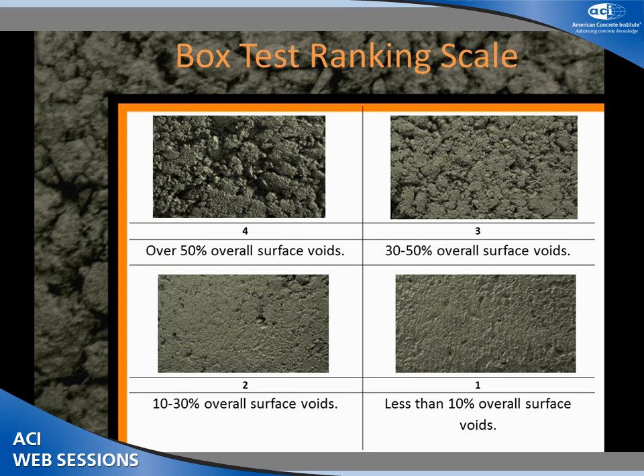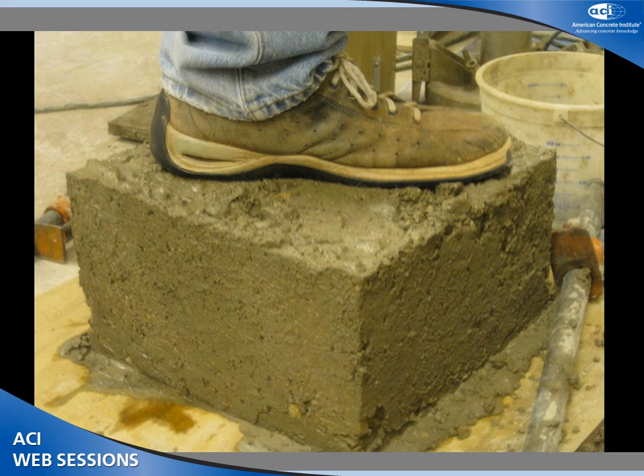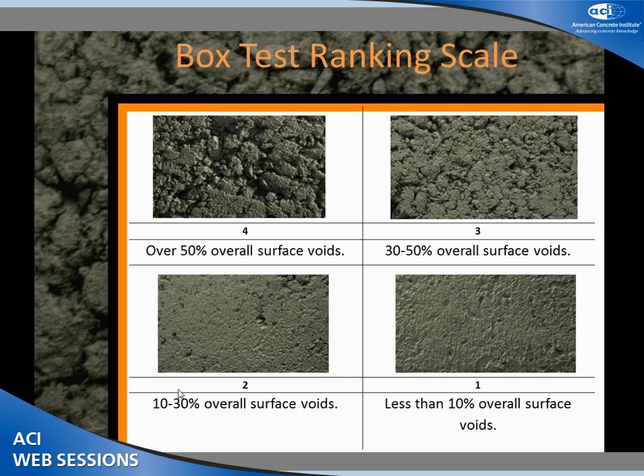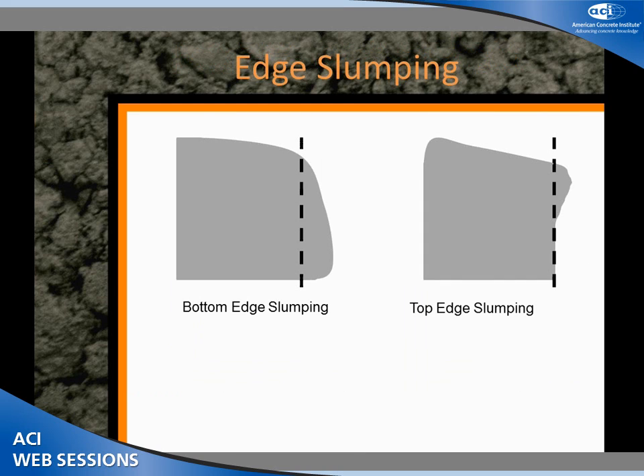There's 2,200 pounds of rock in this mix. So we use visual rankings. We want mixtures that are a one or a two — we don't want a three or a four. We go around all sides of the box, rank each side, and average those rankings together. We're shooting for a performance that looks something like that.